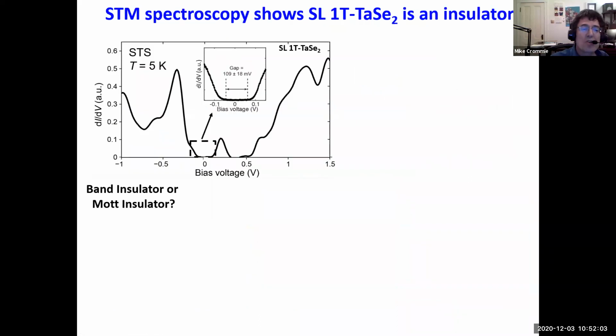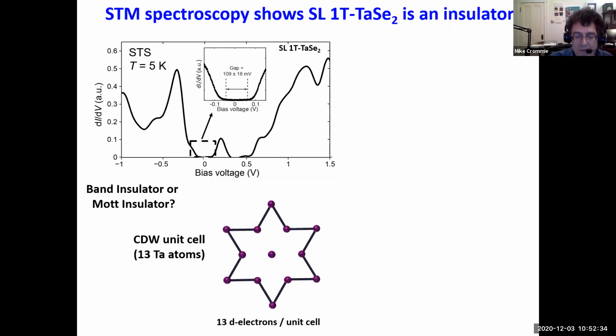And here I show the STM spectroscopy that we measure on this material. This is the STM spectroscopy of the single-layer 1T-TaSe2, and it's an insulator. So it has a nice energy gap of about 110 millielectron volts. Here we have the valence band and the conduction band. So it's a nice insulator, but the question in our mind is: is it a band insulator or a Mott insulator? And that's not completely obvious. So let's think about it for a moment.